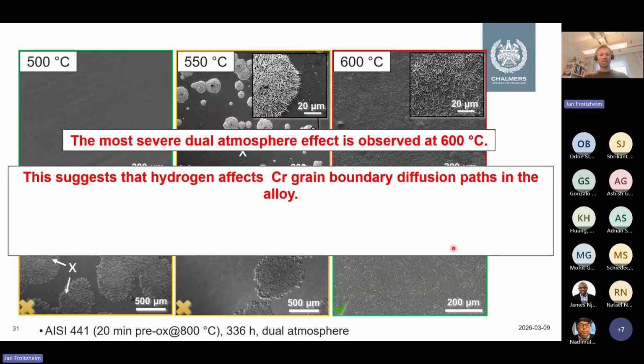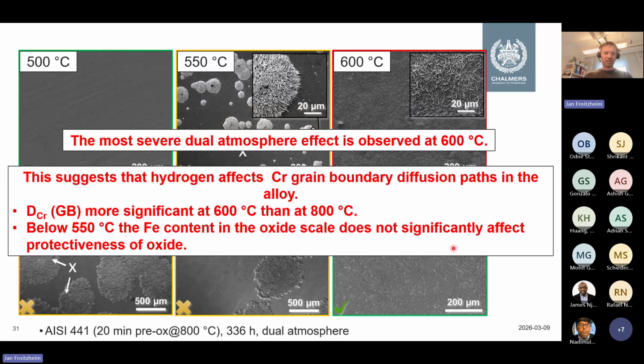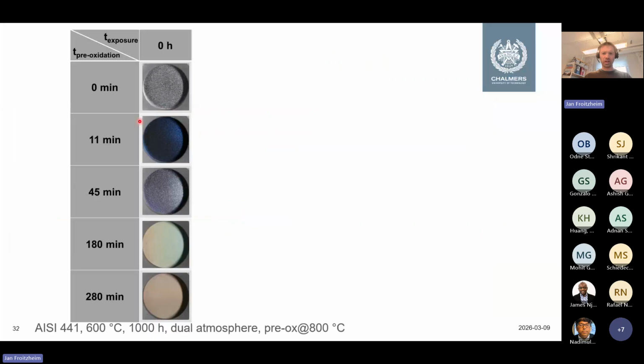This suggests that hydrogen affects grain boundary diffusion paths in the alloy, or that's at least what we speculate. I don't really have time to go into all the details, but the grain boundary diffusion contribution is much more significant at 600 compared to 800 degrees C. And at 550, basically it's too cold for much to happen anyway.